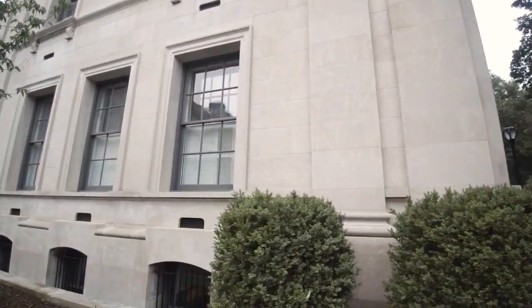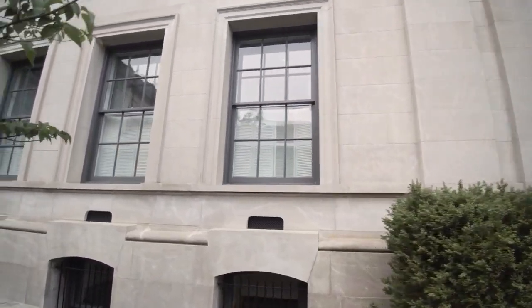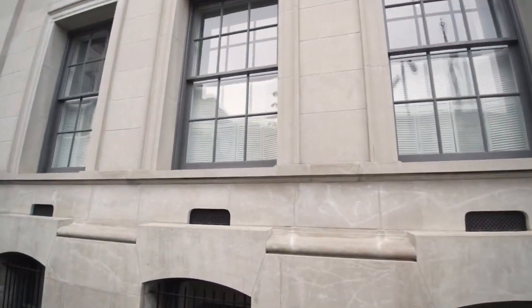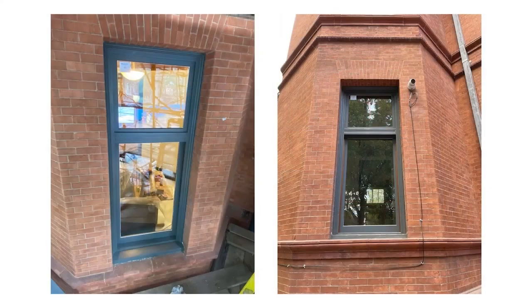Once larger panes of glass became available, the size of windows could also grow relative to the glass. So the 8 by 12 pane came along, and that allowed for a 6/6 to replace the 12/12. These windows had a lot less wood blocking the incoming light and offered much brighter environments. Eventually, the glass was big enough that the 1/1, or the clear view, was born. No muttons in the view, and even more sunlight could enter the home or business. Today, we take a single pane of glass this large for granted.